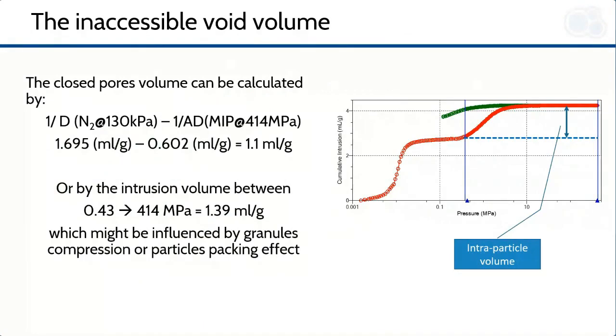The inaccessible void volume inside the granules can be calculated also by taking the difference between the envelope volume measured by nitrogen, thus enclosing the inaccessible voids, and the apparent volume measured by mercury intrusion, when the structure is collapsed at high pressure. The void's specific volume can be also measured by the intrusion volume between the cutoff pressure and the maximum pressure. This last volume is a bit higher, probably influenced by some compression or packing effect.